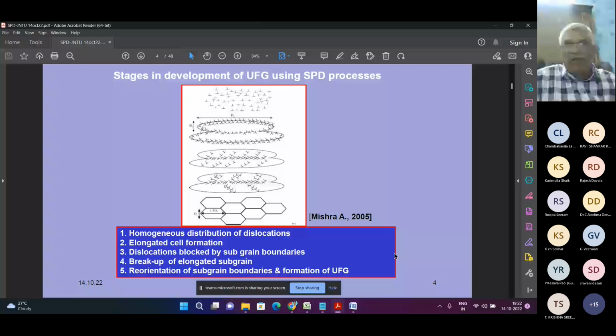When they are changing, you get step two, elongated cell formation. When the elongated cells form, these dislocations are blocked by the subgrain boundaries. You can see in the third stage how subgrain formation happens. These subgrains again break up into elongated subgrains in the fourth case. And finally, reorientation takes place and subgrain boundaries form the ultra fine grain structure. This is generally what ultra fine grain structure means.